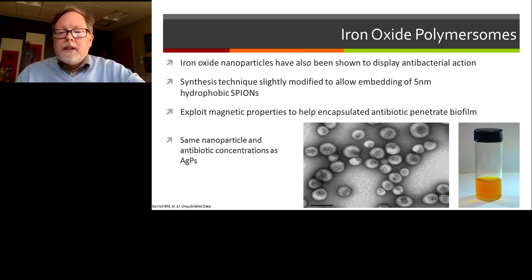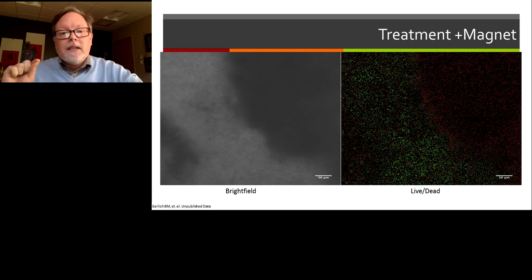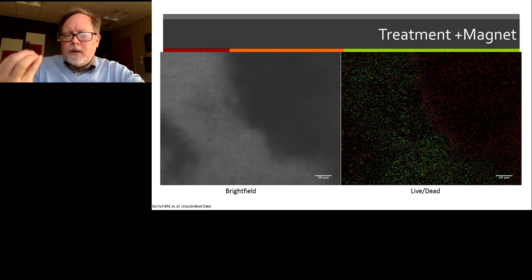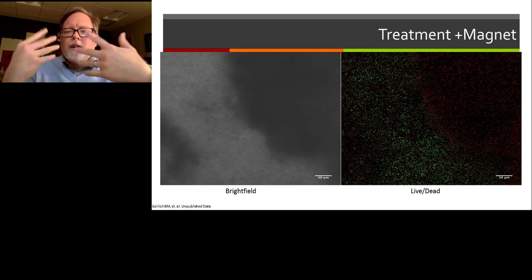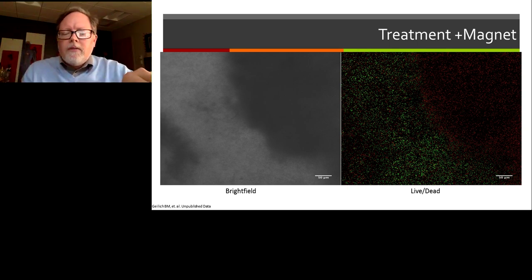Here's a quick experiment to show you how well a magnet does in terms of these iron oxide nanoparticles. These two images are the same field of view. One is a bright field image where you can see the dark black area is a magnet. So we put a magnet underneath a petri dish, we add all these bacteria, grow a biofilm, and you can see, in the bright field image, where that magnet is situated. Again, the same image, just under fluorescent mode, is on the right. And this is what's called a live dead stain.